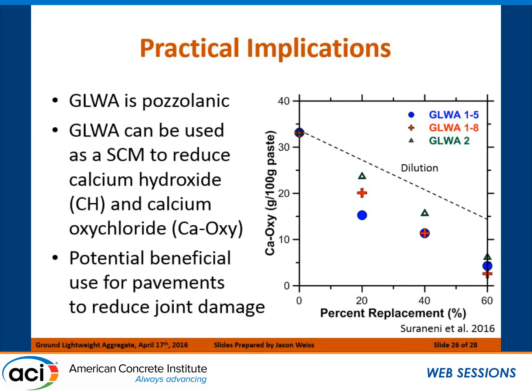Now, when we start to use pozzolanic materials here, we would expect everything, if it's completely inert, to fall along this dashed line simply due to dilution. By taking 20% of cement out of the system, we should reduce the calcium oxychloride by 20% because we reduced the calcium hydroxide by 20%. But the big benefit when you start using a pozzolanic material is you start consuming that calcium hydroxide additionally because of the pozzolanic reaction. So in addition to just not having the calcium hydroxide there, we're gobbling up that calcium hydroxide so that it's not free to react with the chlorides when they come into the system.